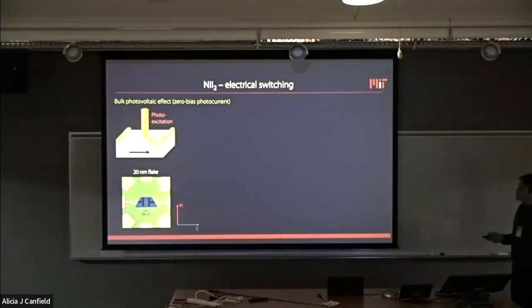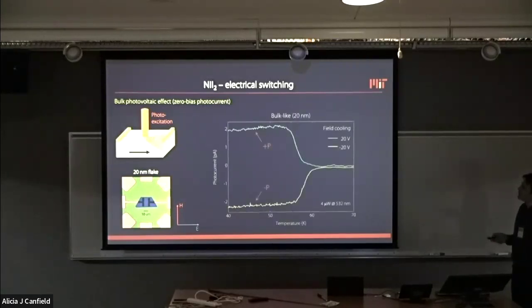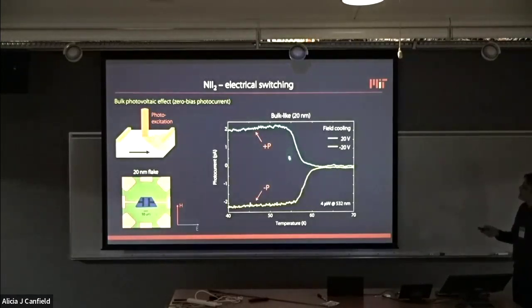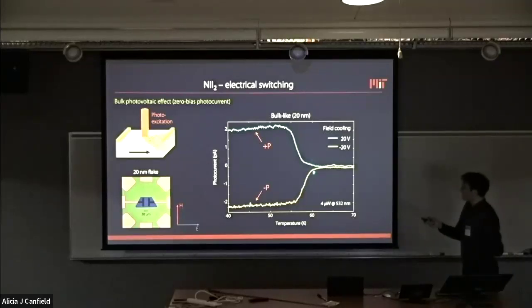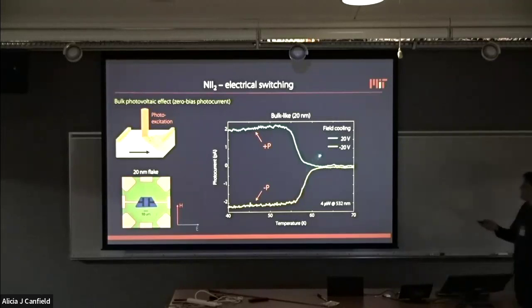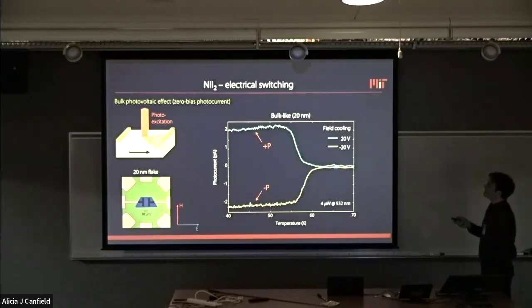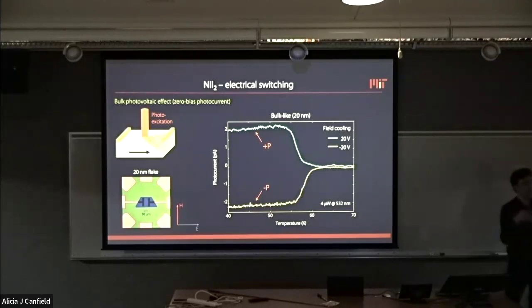So we can use this very simple two-terminal geometry, we illuminate with light, and then we can see that if we do field cooling with positive electric field or negative electric field, this is 20 volts or minus 20 volts, we get two opposite photocurrents that onset exactly at the multiferroic, the helimagnetic transition temperature. This is a very nice probe of the polar states, which is directional too, so it can tell us the direction of the polarization with a specific electrode geometry.